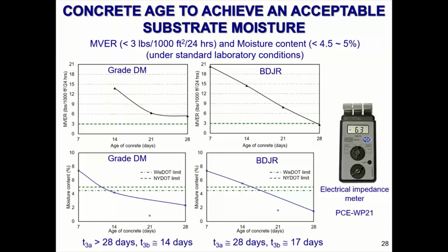This kind of looks at the moisture vapor emission rate. Industry standard for placing an epoxy overlay on a concrete slab is less than 3 pounds per 1,000 square feet in a 24-hour period. We surveyed a couple other states on what they use for moisture content for applying thin epoxy overlays, and we got roughly 4.5% to 5% is the threshold that you have to be under from Wisconsin and New York DOTs. You can see that our grade DM concrete never actually hits the moisture vapor emission rate industry standard. But to get underneath the moisture content percents that a few other DOTs use, our grade DM concrete hit that in 14 days, and our grade BDJR concrete hit that in 17.